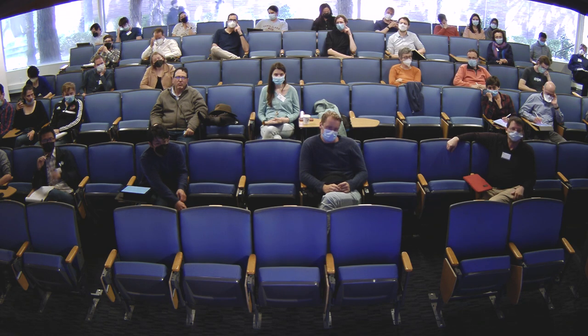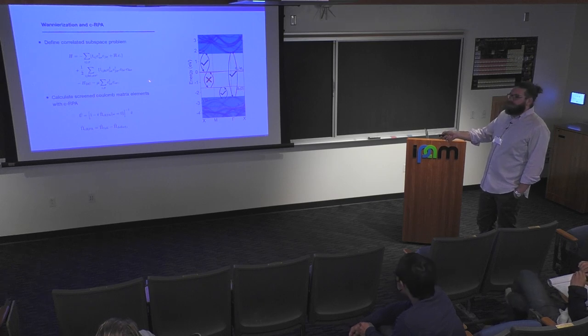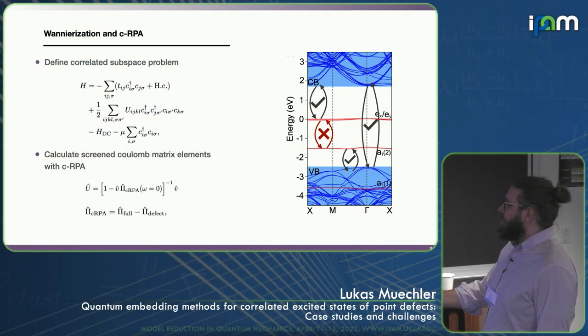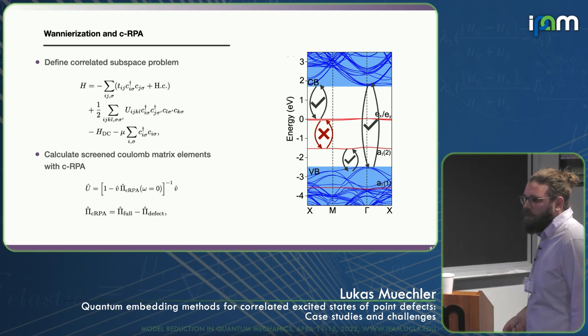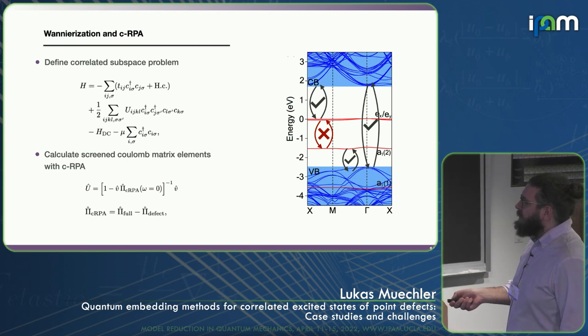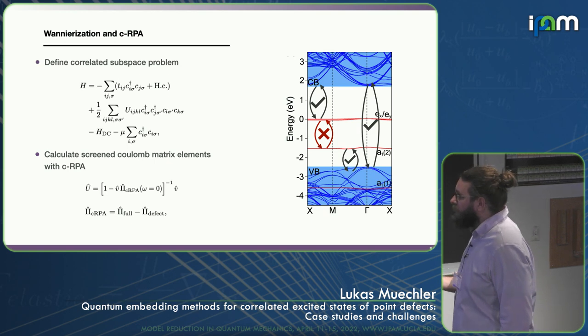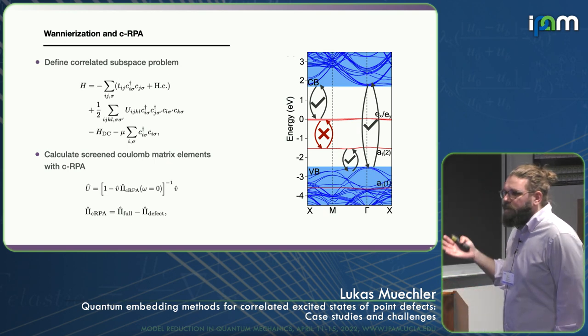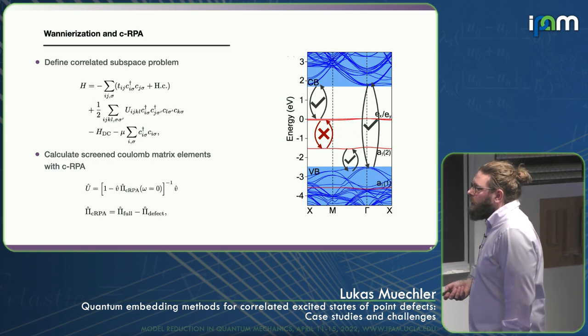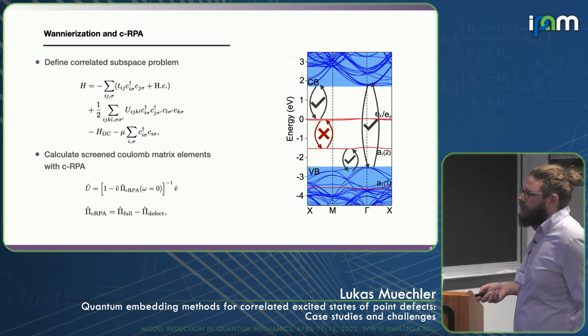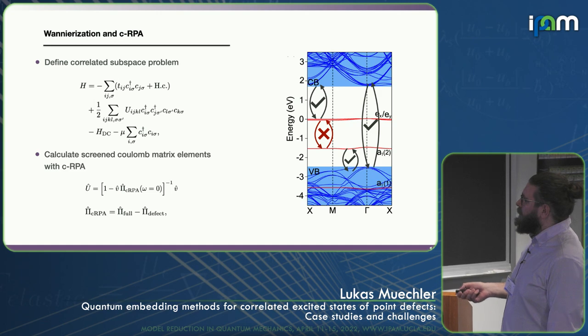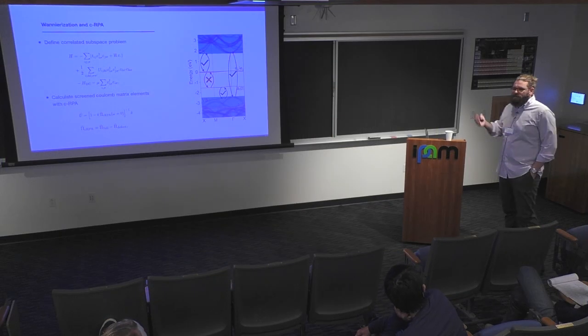We start with the Wannier functions, calculate the bare Coulomb interactions, then use the CRPA polarization to get the screened Coulomb repulsion. In general this screened Coulomb is frequency dependent, but we just look at the frequency independent omega equals zero value. This approach has been extensively used in DMFT to describe strongly correlated crystalline systems. A practical bottleneck is that normal RPA scales with system size to the power of four, with large pre-factors, especially if you need to store things on a high frequency grid.